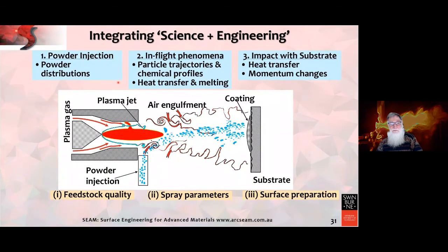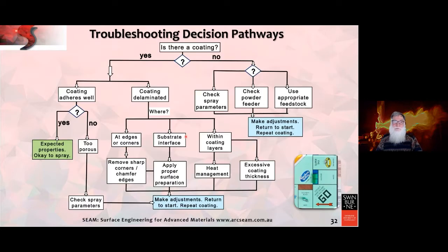So here we have our torch. Roughly we've got powder injection, in-flight phenomena, and then we got impact with the substrate. And the things that we can control would be feedstock quality, the spray parameters, and the surface prep. And this all happens within a few milliseconds during the spray process.